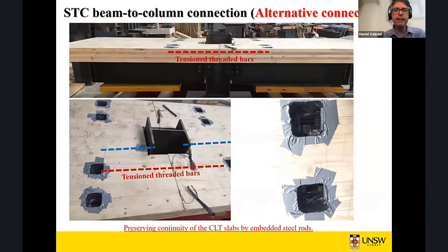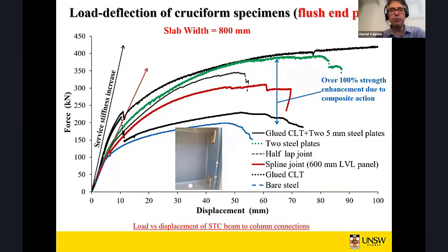Again, we came up with some other alternatives for connecting the CLT to CLT at this location, where the two panels meet each other at the column joints. We use this method, which is basically embedded threaded rods, and we got very good results out of it. You can see, again, we use these shear pockets, we fill them with, let's say, cementitious grout to protect the bolts or mechanical shear connectors from exposure to whatever is outside, including possible fire, etc.